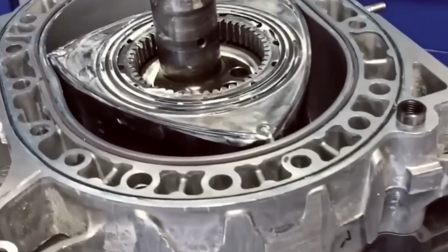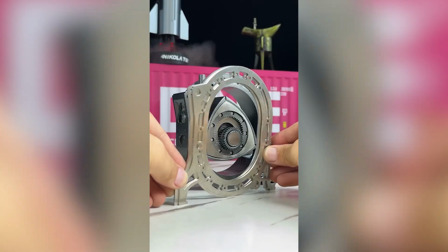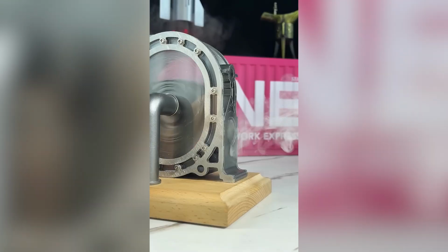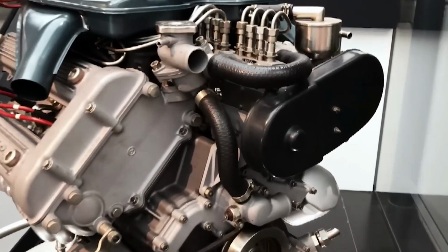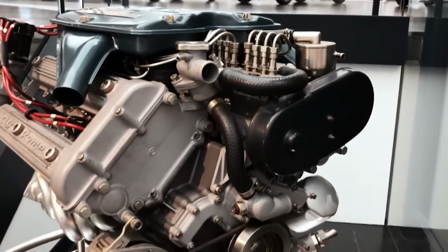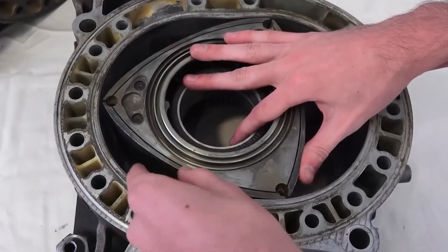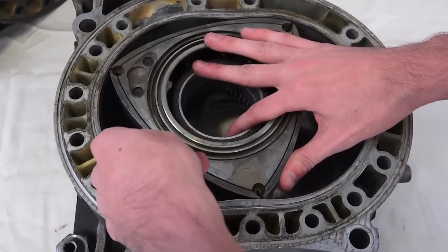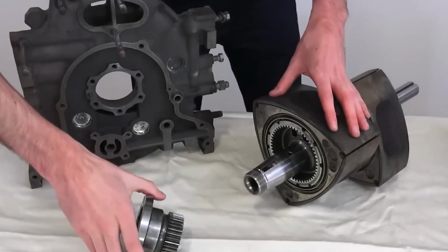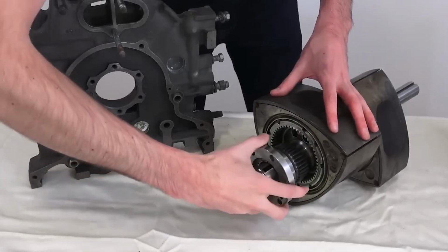The problem was the apex seal, a tiny triangular component smaller than your thumb that had to maintain perfect contact with the rotor housing while enduring temperatures exceeding 1,300 degrees Fahrenheit, pressure differentials of 1,000 psi, and sliding velocities that destroyed conventional piston rings. Detroit attacked it with brute force.